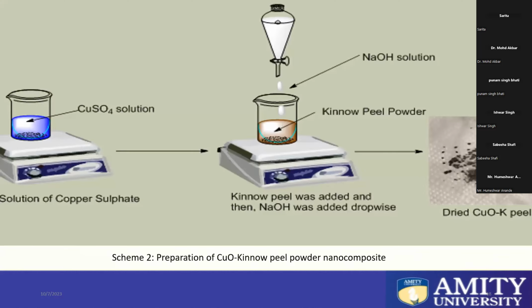Once this powder was formed, we treated it with the metal precursor solution, that was copper sulfate solution. So we took the copper sulfate solution. To that, we added about a gram of Kinnow peel powder, which was prepared by the previous scheme. To that, we added dropwise with stirring the NaOH solution, and we got a sudden change in the color of the solution, and we got a dark color precipitate, which we consider to be the dried composite of copper oxide Kinnow peel powder.